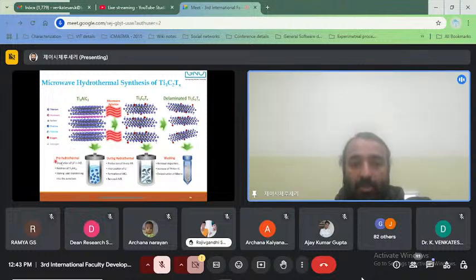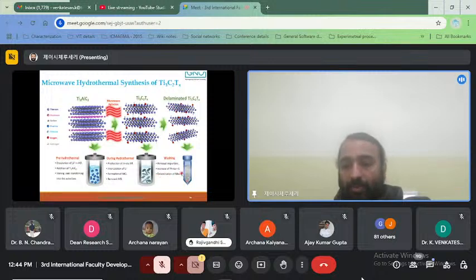So first we dissolve that MAX phase in the LiF HCl mixture. Then we stir and send it to the autoclave. Then we use the microwave hydrothermal reactor. So there will be production of in situ HF, intercalation, and formation, and then removal of aluminum chloride from the structure. This is how we remove aluminum from the titanium aluminum carbide MAX phase. Once we wash it multiple times, the pH should be more than 5, and finally we get a delamination of MXene.